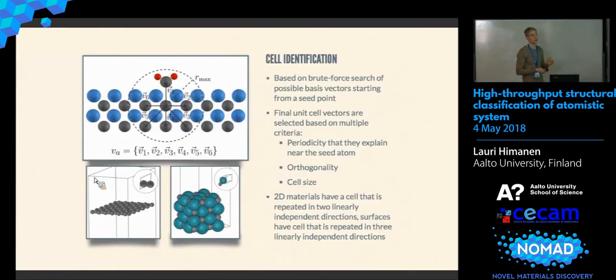And now by simply analyzing how many clusters we end up with, we can identify the dimensionality. So for 0D, we start with one cluster, and after the expansion, we end up with 8 clusters. This determines that it's a 0D structure. And for the other end of the spectrum, we have 3D structures, where if you start with one cluster, do the supercell expansion, you end up once again with one cluster. And then there are 1D and 2D examples in between, where we have 4 clusters and 2 clusters. So this is a simple idea of determining the dimensionality of these fully periodic systems.